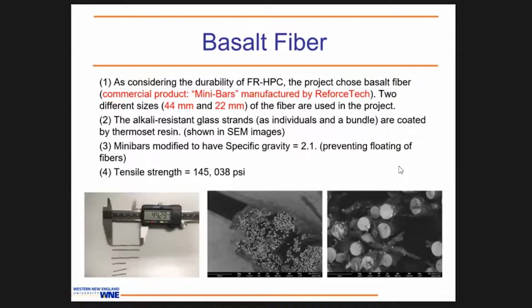So we chose these 2 minibars, and we also looked at the SEM images to see whether they are well protected against alkali resistance issues. When you take the SEM images, it's well coated, so we don't need to worry about alkali reactions later on. Also, one of the things that we worried about is the segregation of the minibar when we are mixing the concrete. They said that at the very beginning, if you are using the shear mixer, maybe minibars will not survive well. So we looked at the specific gravity. Again, there is no segregation, as it is well mixed with our shear mixer. It is working fine.